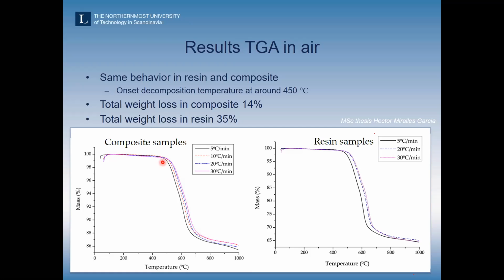There is a degradation onset of decomposition at around 450 during these short-term tests, both for the composite and the resin samples. When we run it up to 1000 degrees, we notice a rather small decrease in weight, comparatively small at least, 86% during this mass loss. So it's not completely combusted even up towards high temperatures like this. And we have 65% of the resin samples after completion of the neat resin samples. These are done in air.